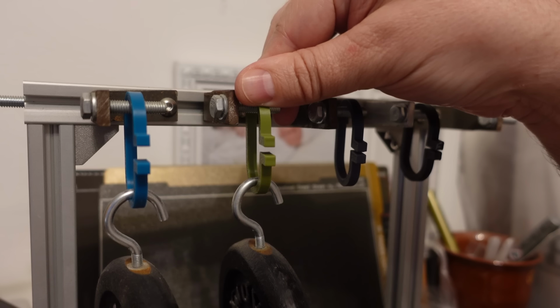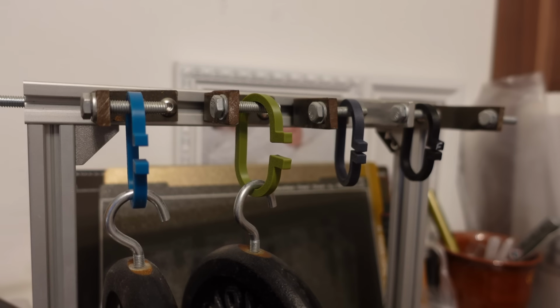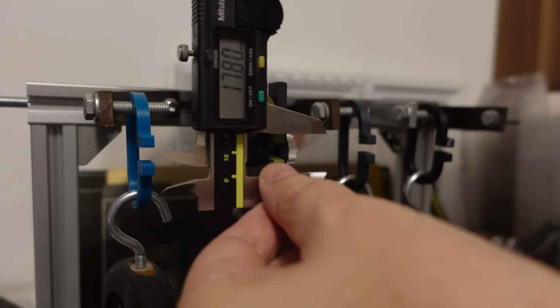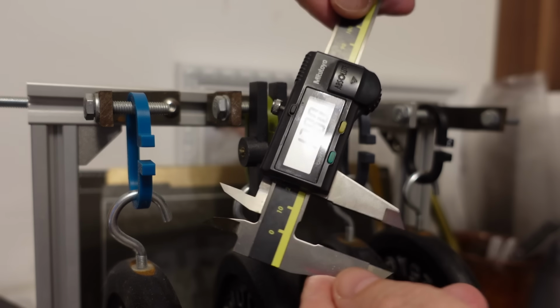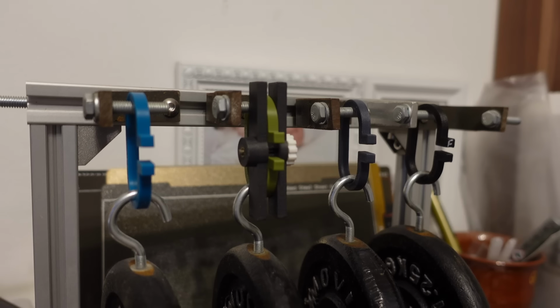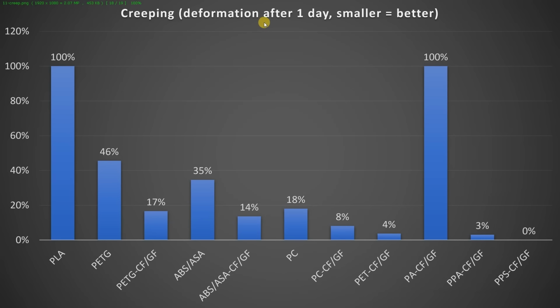Creep, the deformation under constant load, of 1.25 kg in this case. I'm locking the position and I'm measuring the distance between two reference surfaces daily for the next 5 days. And here we can see the deformation after 1 day. Smaller is better, and we can see the biggest disadvantage or weak point of the PLA.